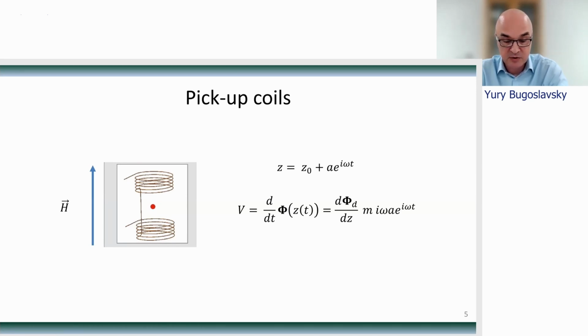The schematic shown here is what is usually used in so-called longitudinal VSM, where the direction of the sample movement is parallel to the direction of the applied field. In this geometry, the best configuration contains two pickup coils. The coils are connected in such a way that they are sensitive only to the field generated by the moving sample. Other effects, which may occur, for example, due to instability of the applied magnetic field, are greatly reduced and